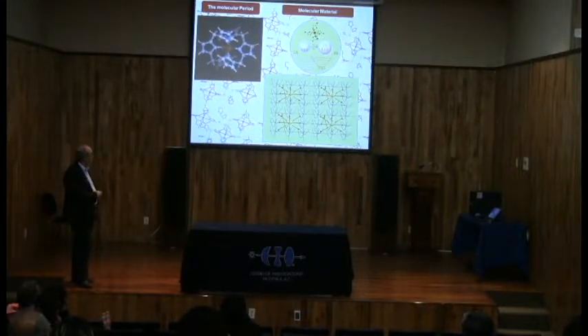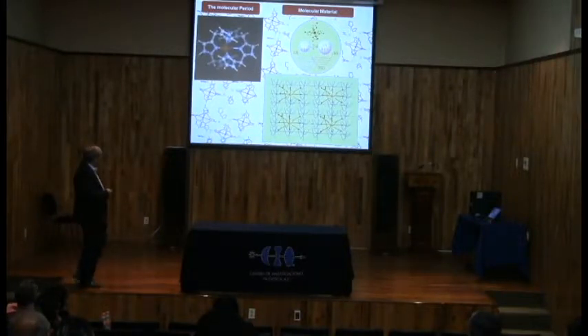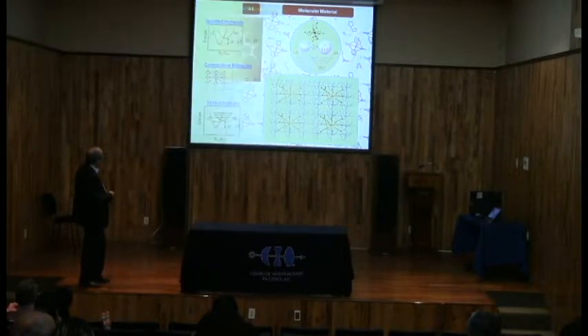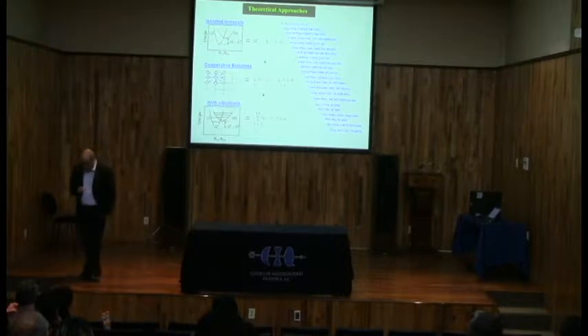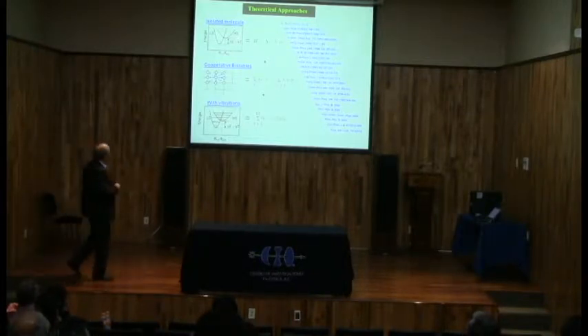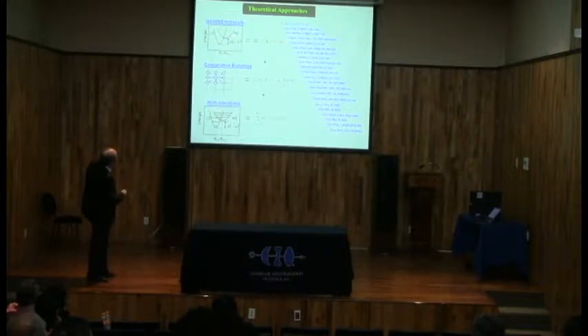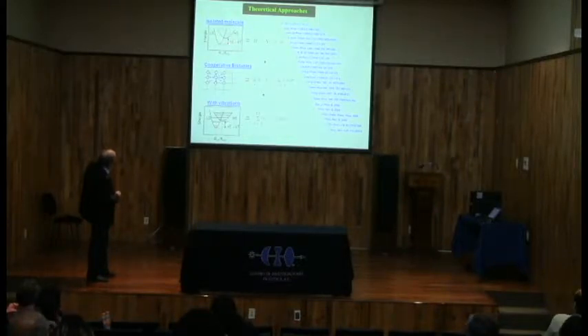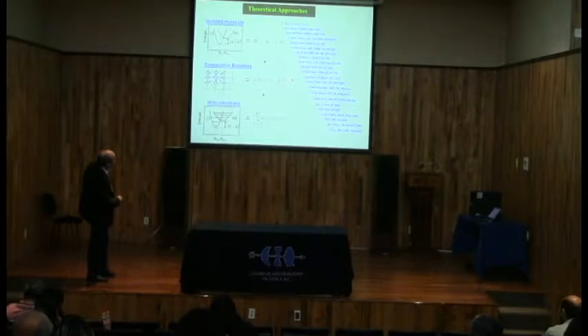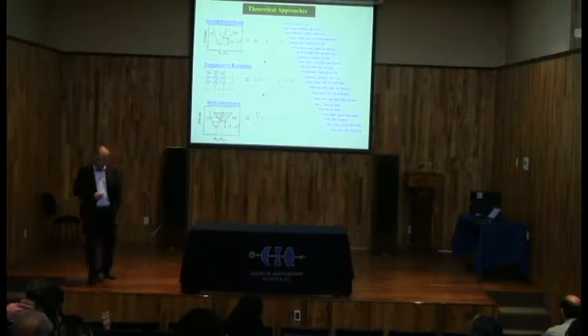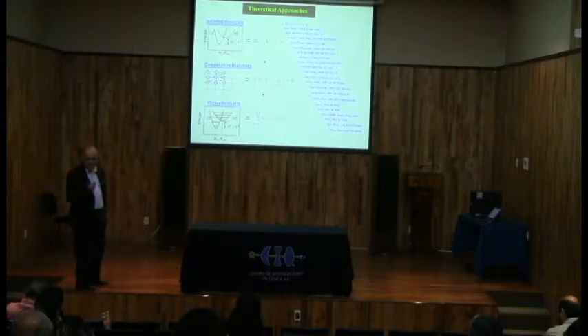And then you can think about the transmission of the information, the propagation of the switching through the crystal, and you can think about many approaches concerning the switchable materials. Theoretically talking, if we wish to synthesize this, we say that in the spin crossover system the molecule is a double potential, so we can use a Hamiltonian which is one fictitious spin system that describes just the energy gap. And if you go to the network, to the crystal, you have to add the interactions by J sigma sigma, which is the Ising-like model formalism, where J has an elastic origin.